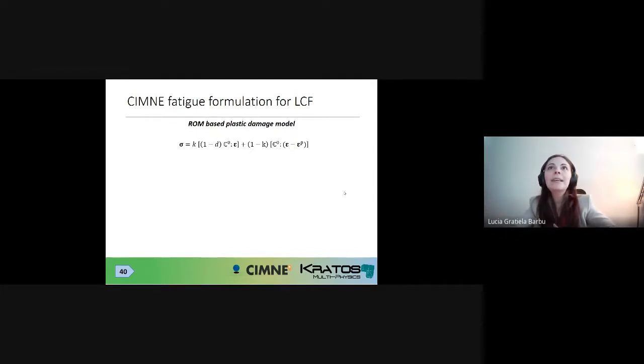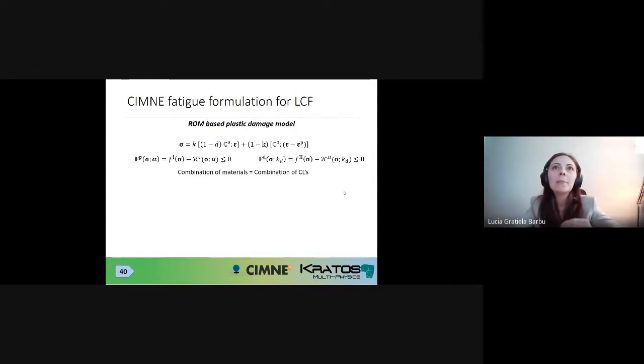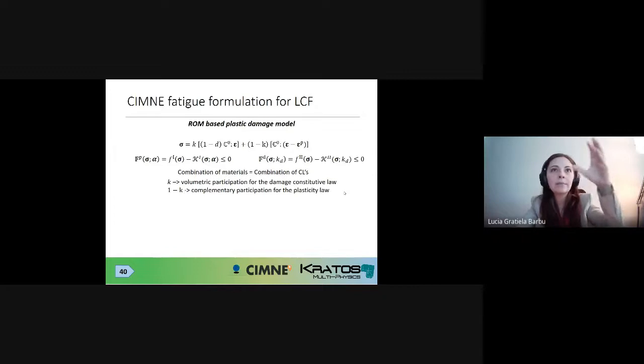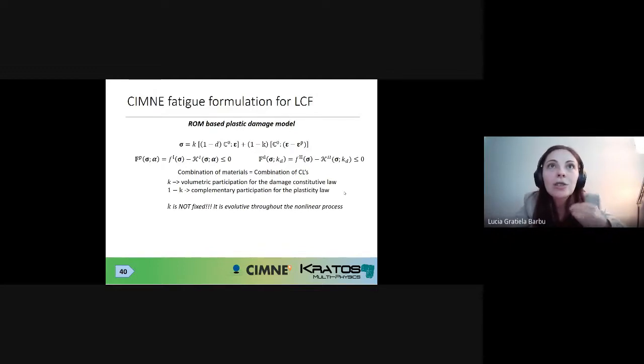This is very interesting and very clever, because it allows you to play with these participations and understand the behavior of homogeneous materials, not as a combination of materials, which was done for composites where you had fiber and matrix, but as a combination of constitutive laws, of constitutive behaviors. And the interesting thing here, with complementary volumetric participation for the damage and plasticity, is that this volumetric participation is not fixed. It's evolutive throughout the nonlinear process.